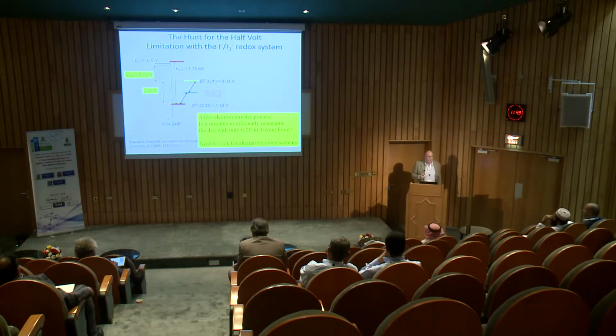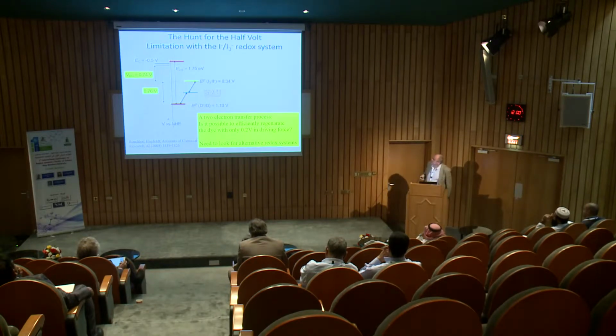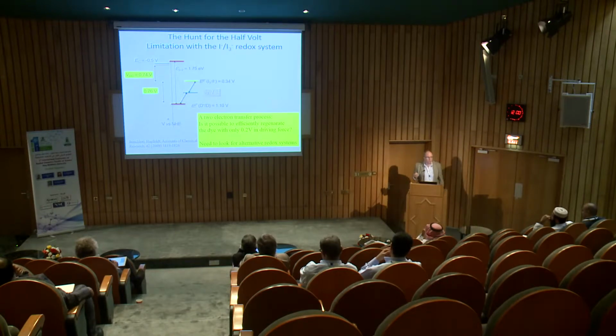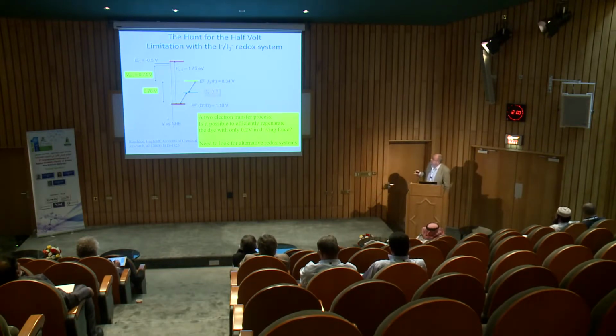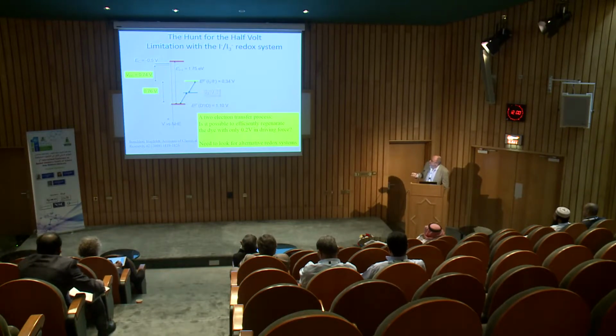It started some years back, and the question was where, in the conventional dye-sensitized cell, based on the ruthenium complex, the iodide electrolyte, TiO2, is the main internal potential drop in the cell. And it was nothing particularly strange. We know it almost from the start in the 90s that we do have a large internal loss in potential when we take the electron from the electrolyte to the oxidized dye. This is what we call regeneration of the dye. There we lose in the iodide system about 0.6, 0.7 volts. The question was, why do we need so much potential in that step? Can we reduce it and in that way gain more efficiency? And in principle you can do that in 2 ways. Either you change the dye, so you move your HOMO level of the dye, the ground state, up here, so as to minimize the potential drop.